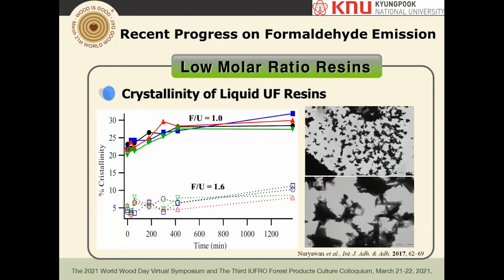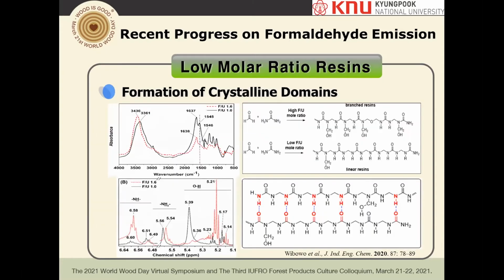And then we also look at what was happening in the liquid resin, and then we look at the XRD for liquid resin. So as expected, the low molar ratio has about 28%, which is smaller than the cured one, but still they have crystallinity. And then we also luckily found crystal particles in the liquid resins. That means most of the crystals in the liquid move to the cured resin, and they aggregate into much bigger crystals with high crystallinity.